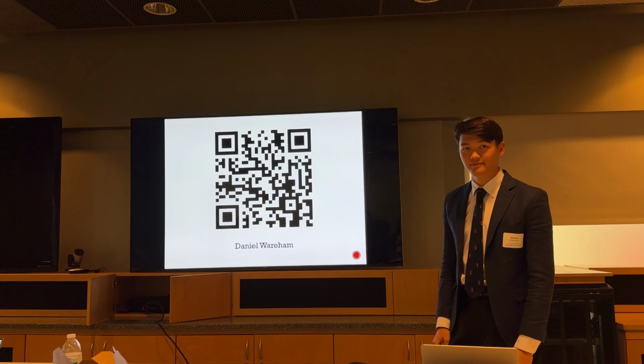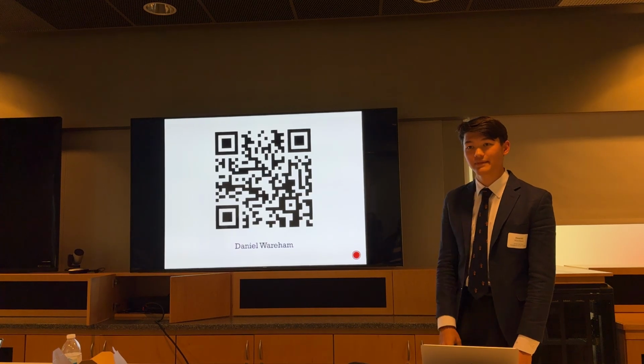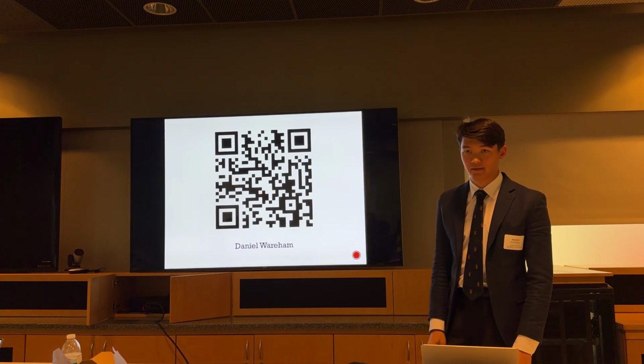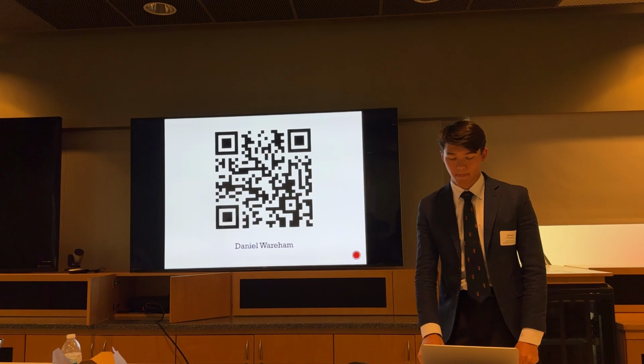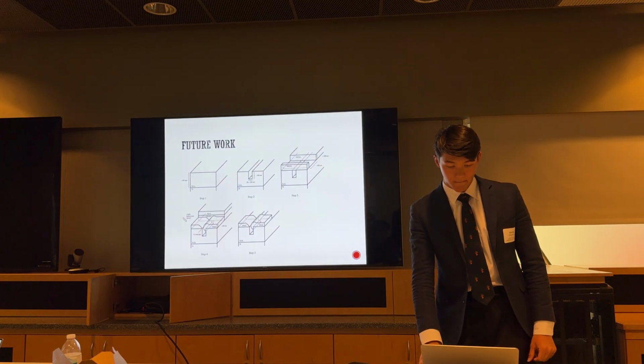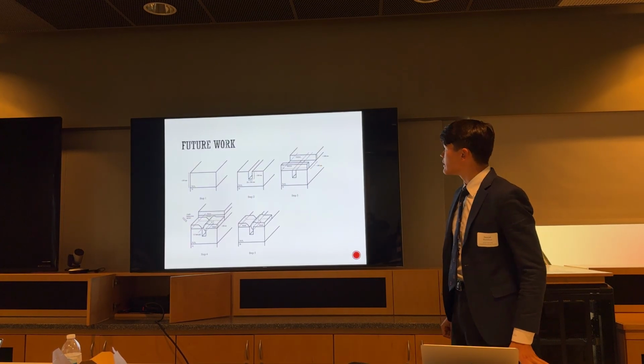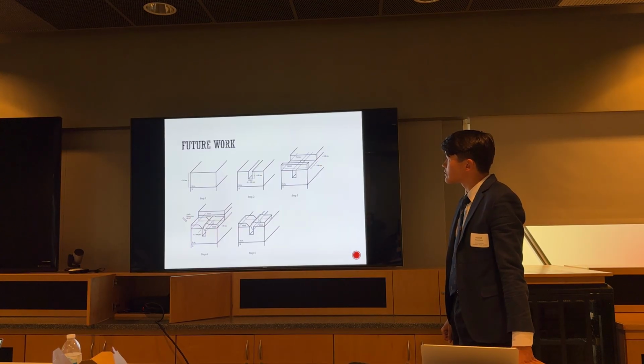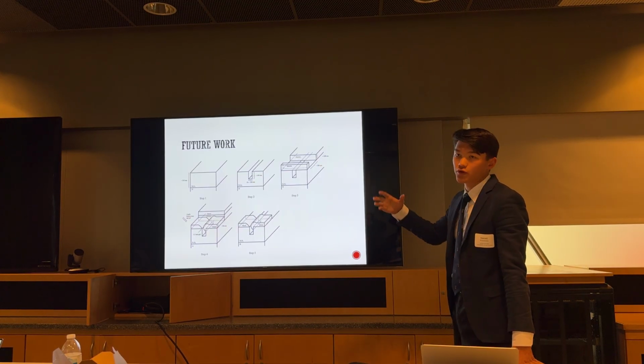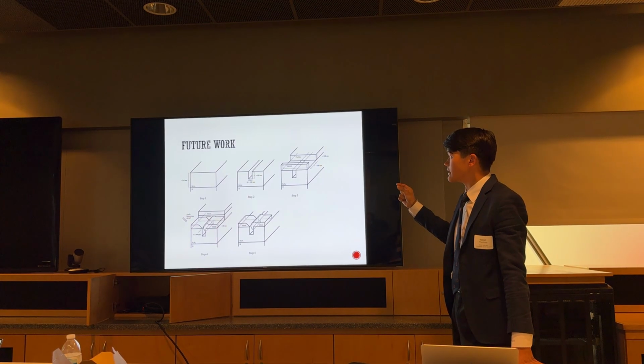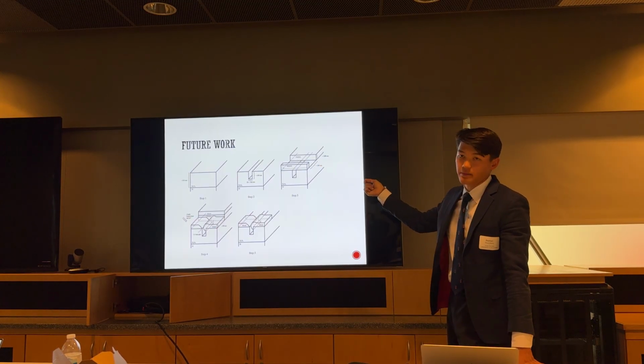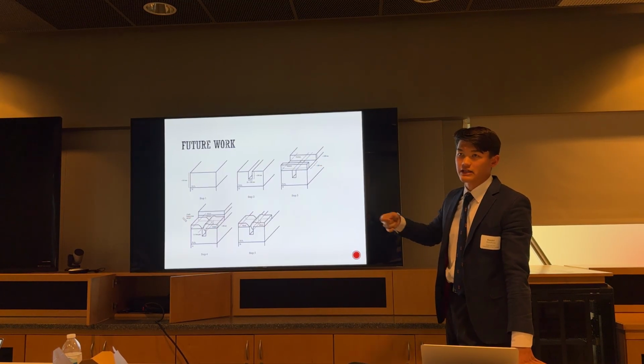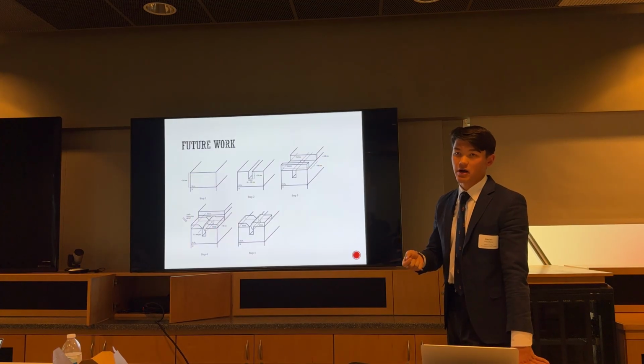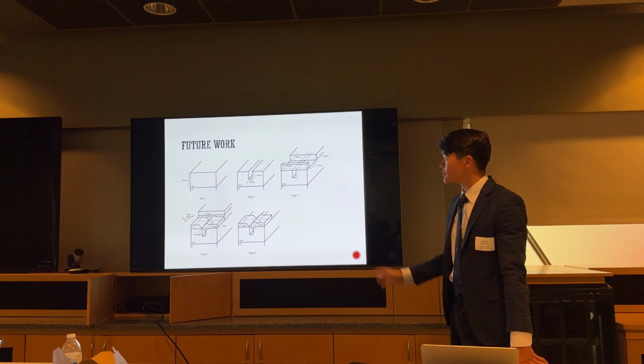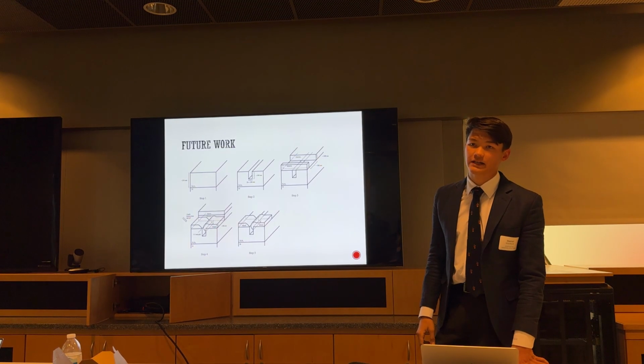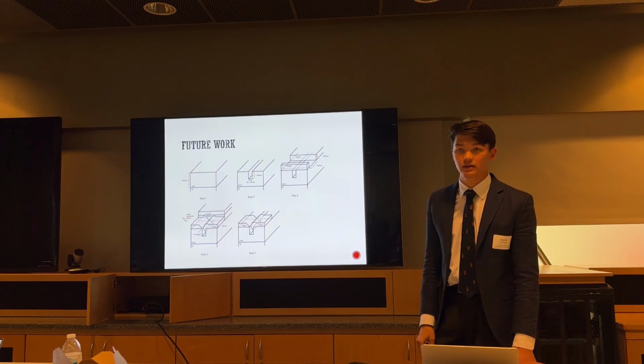Questions? What was the reason for the choice of having 200 nanometers of ytterbium fluoride and the 100-nanometer trench, versus having a full trench, if you don't know how deep it is? Those aren't specific parameters, they're just order of magnitude numbers. The specific numbers aren't really determined by these diagrams, and these are things that really require experimental findings. So this is really just to give a sense of order of magnitude.